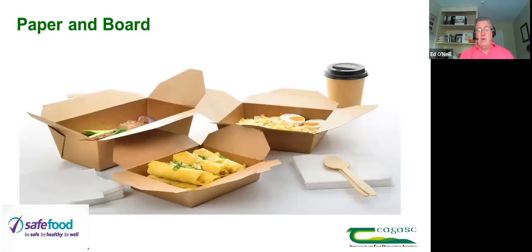First developed in the 1700s, paper and board can only be recycled 5 or 6 times before the fibre length gets too small and it has to be sent for energy recovery, either in cement kilns or separate incineration facilities. Paper is used throughout the packaging industry, mostly as a wrapping material or as a laminate in pouches. Plain paper itself is not used to protect foods for long periods of time because it has poor barrier properties and is not heat sealable.